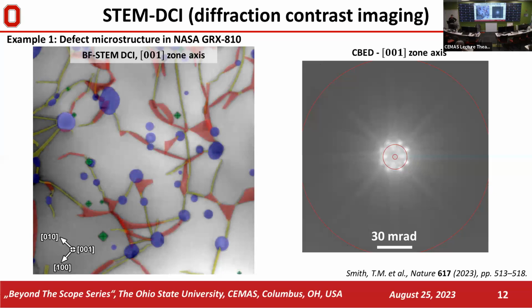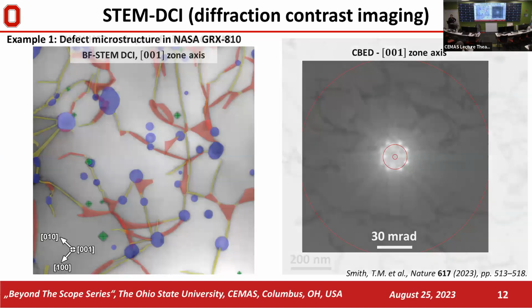So when you cross-correlate with other techniques like EDS or atomic resolution imaging, you can get information about the dispersion of different structural features, like where the oxide particles are, where the unit dislocation lines are, where the stacking fault tetrahedra are, where the dissociated faults are. And this is what's differentiated here by color. So this is zone axis imaging.